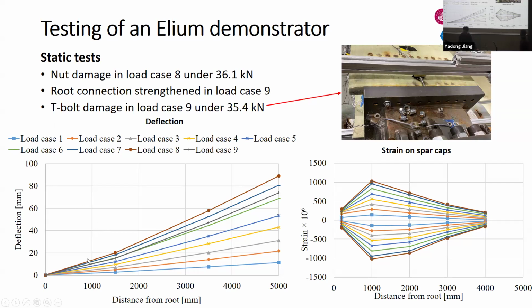In terms of the deflection, we have 9 deflections, and if we compare the deflections of this Elium demonstrator, which is recyclable, with the epoxy demonstrator, which is not recyclable, we found the deflection before failure is roughly, I wouldn't say exactly the same, but within the same range. This indicates that both demonstrators have similar stiffness, and that means it is very promising to replace epoxy with Elium to manufacture recyclable large composite structures.